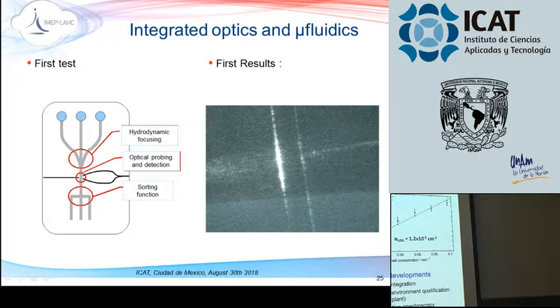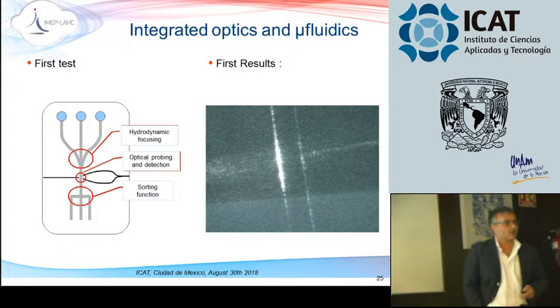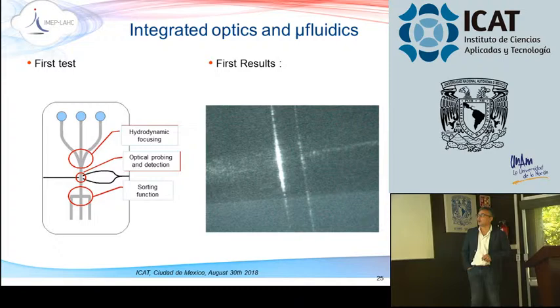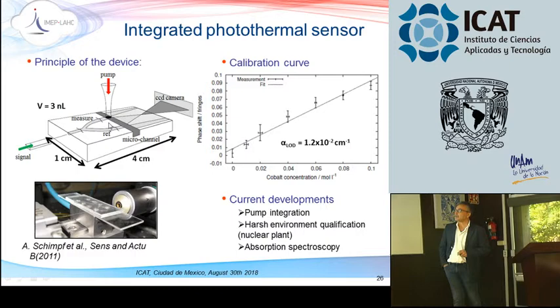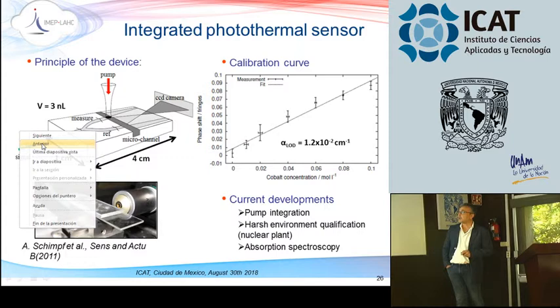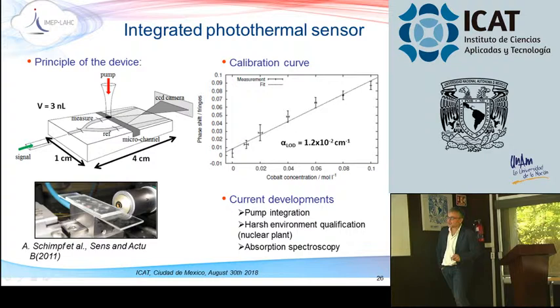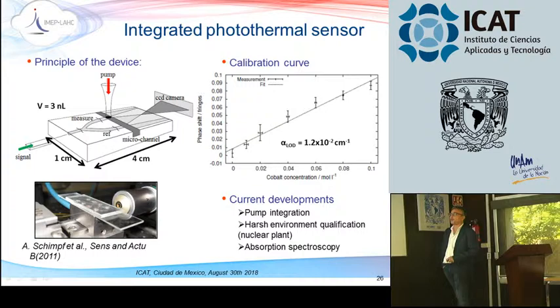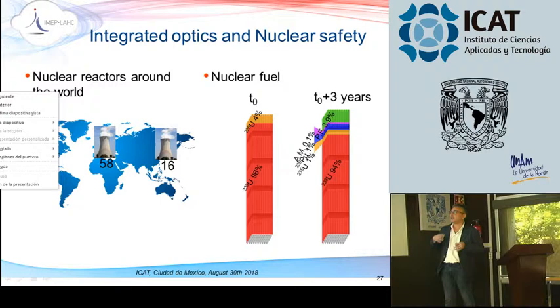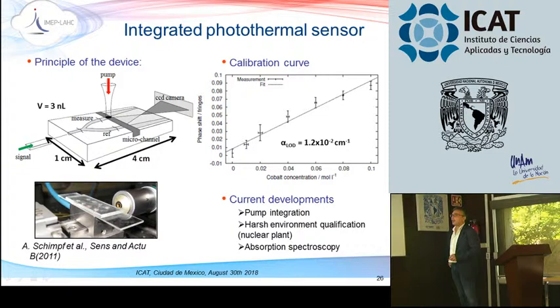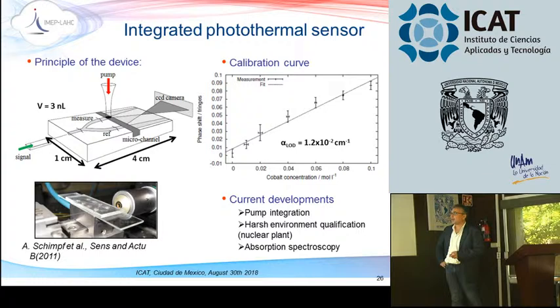Practical applications just arose when we were contacted by people dealing with devices operating in a harsh environment. So we did, for example, a photothermal sensor. The idea was to create a microchannel and make a Young interferometer, and then measure the phase shift created by the absorption of an element. And with this, we made a sensor that is quite small, with a volume of only 3 nanoliters of solution, and you have a calibration curve, and it allowed measuring things. For example, we measured cobalt and other elements in alcohol. So it was a good device, but not so impressive.